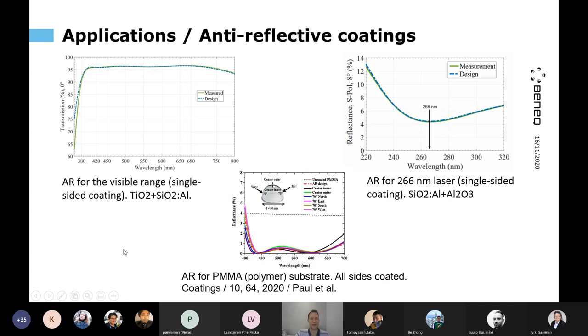Moving on to more of the applications side of things. The most common thing for any kind of optical coatings is anti-reflective coatings, to reduce the reflections. Here is a typical example of a glass with a single side coated with an AR coating, broadband for the visible wavelength range, using titanium oxide and one version of the silicon dioxide that we have. Then comparing the graphs here, the design and the measured. When they overlap nicely, then we are happy: first of all, we know our materials, and secondly, we can manufacture as we designed.